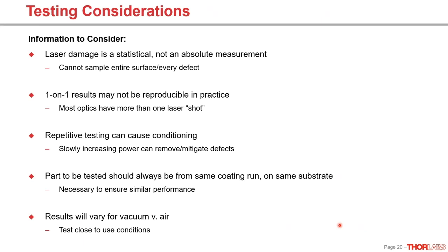Repetitive testing can also cause conditioning. And this is similar to, as I brought up before, the ejection of defects. So if you do that, you can eject some defects that would cause the part to fail at higher power levels. So that's something to bear in mind.